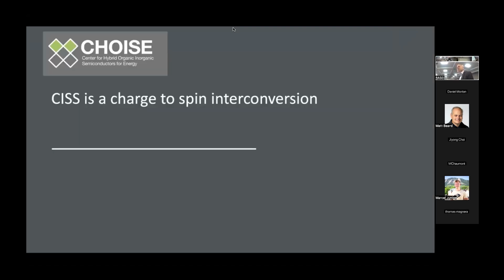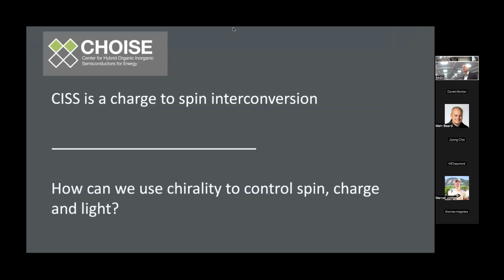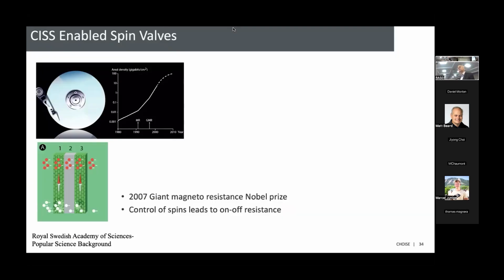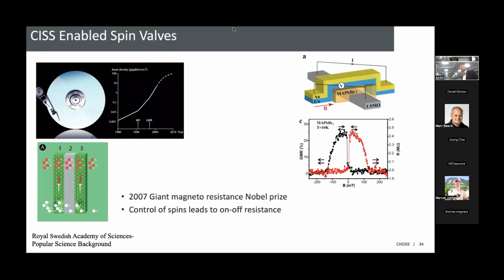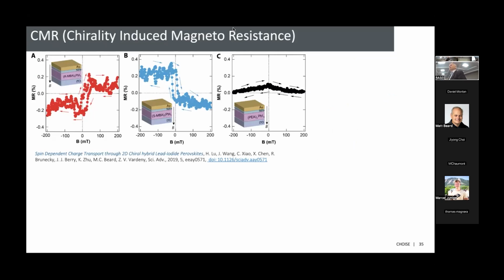All right, so this is a charge to spin interconversion process. So how can we use this chirality to control spin, charge, and light? There's a couple of ways. There's a phenomenon where we can do CISS-enabled spin valves. This spin valve was awarded the Nobel Prize, and it makes up all of magnetic memories, but it's based on two ferromagnets. So if you have these ferromagnets, you have a low resistance state and a high resistance state, depending on the polarization of these two ferromagnets. So that's the idea. But with CISS, we can take one ferromagnet away. We can make also a spin valve. We have a low resistance state and a high resistance state, and it depends on the chirality.